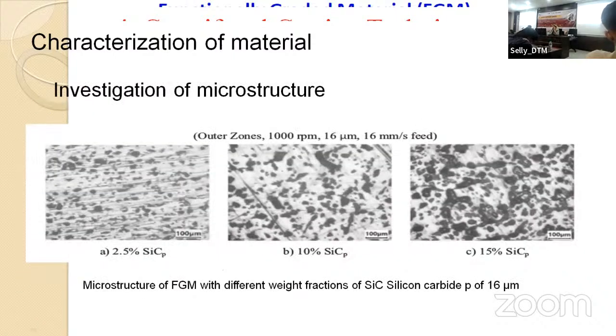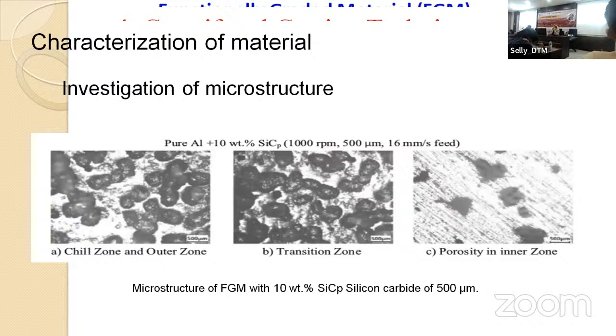You can see a microstructure of the functionally graded material. It's for silicon carbide, at that time its particle size is 16 micrometers, and then the biggest one, if we choose the silicon carbide of 500 micrometer. They get a microstructure. But I want to show you this structure is the outer zone and this structure is the inner zone, and the transition structures, both of them.